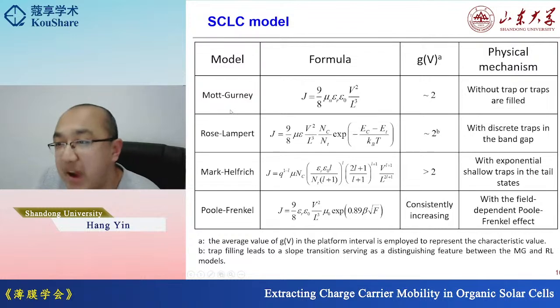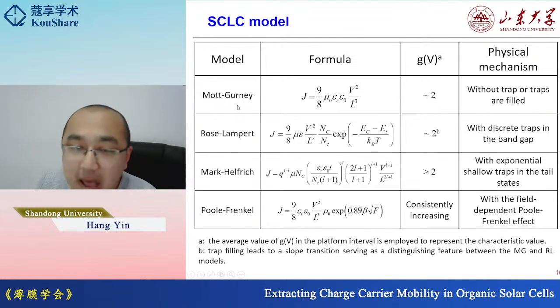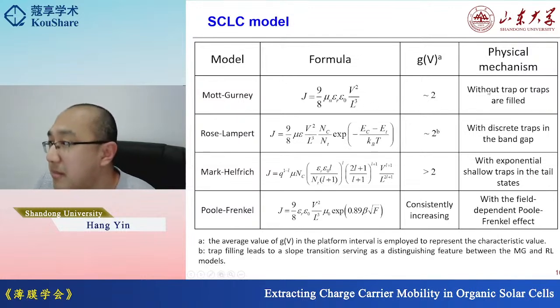Okay, from the very beginning, I think many papers just use the MG model. The reason is the MG model is very easy, right? Because the physical mechanism means there are no traps or the traps are already filled, so we can just fit at relatively high voltage. But we cannot confirm every electron-only or hole-only device is trap-free, right? So the mobility values should be different. And other models, for example, the MH model or the Poole-Frenkel model, can also be adopted under different conditions. And here it's very interesting for the Poole-Frenkel effect, because many people use the PF model to fit the mobility values.